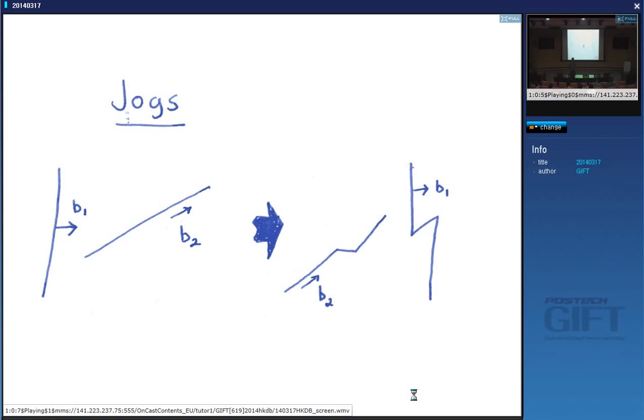So if I told you, do you get martensitic transformation in plutonium from a cubic to a monoclinic structure? If you can find one fully coherent line between the two crystals, it would be possible to get martensitic transformation. If you cannot find a single coherent line, you cannot get a glissile interface. So we call such a line a fully coherent line between the parent and product lattices. We call that an invariant line.